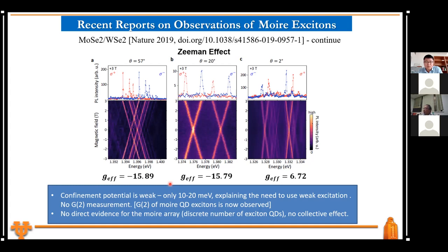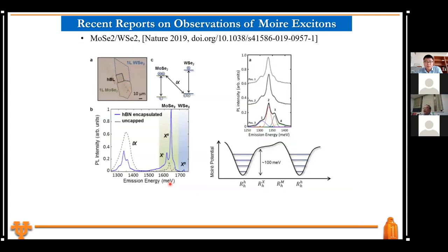But in all of this early moiré exciton study, because of how you fabricate it, there's no direct structural confirmation. All right. Then this is by Elaine's group, and they study the same system, okay? And they observe very different phenomena. Their conclusion is that this moiré potential is rather deep, resulting in this multiple level confinement, all right? At this moment, I still cannot say who is correct, even 3 years after this.